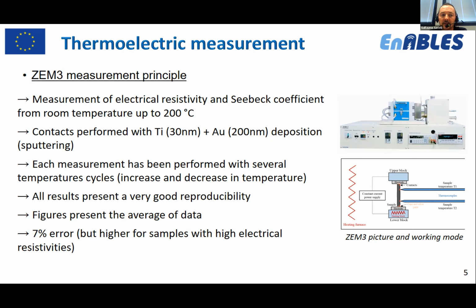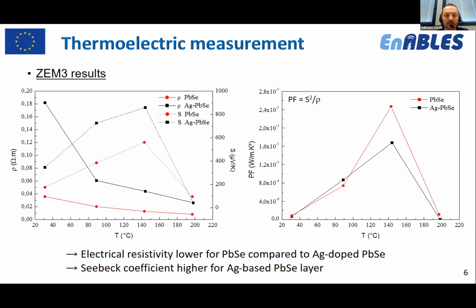The contacts on samples were performed with titanium and gold deposition to obtain good ohmic contact. Each measurement is performed with several temperature cycles, and they presented very good reproducibility. And with this tool, we usually obtain 7% error in measurements. So you can see here the results we obtained.